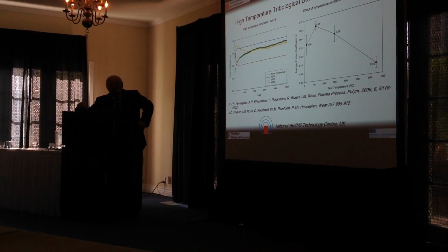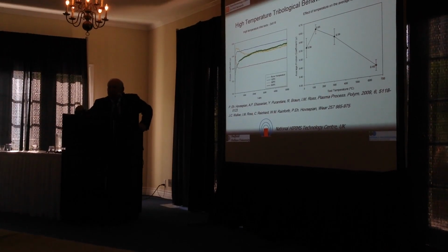Very interesting properties. We saw first sign and signature of oxidation after 850 degrees C. Hardness was retained up to 900, very high hardness. Very interesting tribological performance. With temperature, the friction coefficient in high temperature tribological test was reducing. This is very well understood because the oxides which form based on chromium are so-called magneli type of oxides, so they have low shear stress planes, and therefore the friction coefficient is reducing because you produce these lubricious oxides.